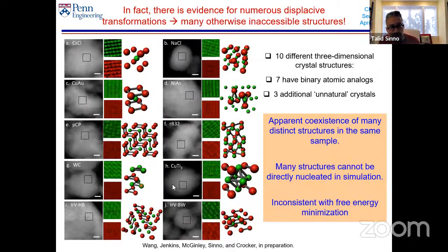And by the way, I just want to show this picture. Subsequently, John Crocker's group actually went through and tried a whole bunch of different size ratios and different stoichiometries and showed that this happens quite ubiquitously. It happens quite generally. This is the copper gold here, but they were able to make a whole bunch of different configurations that clearly came not from a one-step nucleation process, but rather nucleation of a parent phase followed by transformation to a child phase. So this happens and others now have seen this in several other systems. And so one starts to think, maybe we can use these as transformer crystals that can undergo different phases depending on the ambient conditions. So that's why we got interested in studying this.